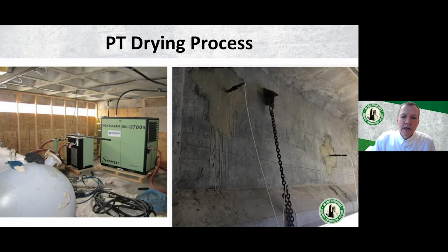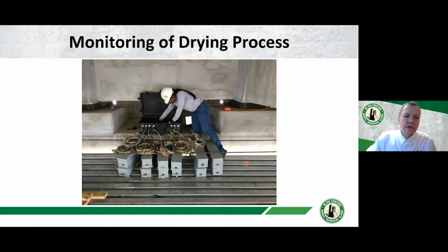This in here, you can see going into one tendon here, you can see a tube connected to a different tendon down here, and you're going to pump the dry air in at certain locations, and it's going to vent out at other locations. And at the vent locations, you can manually measure the moisture content, or as illustrated here, you can have an automated system, and you basically are monitoring the moisture content of the air that is being exhausted throughout the process. And as I said before, you continue the drying process until you get the exhaust air down to the level of dryness that you wish to achieve.